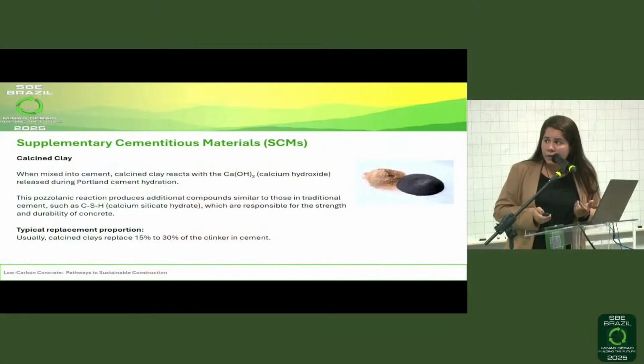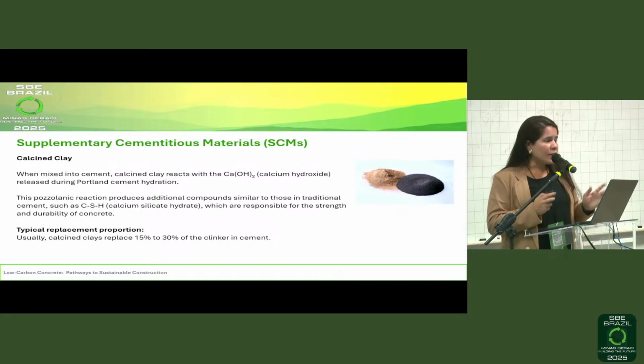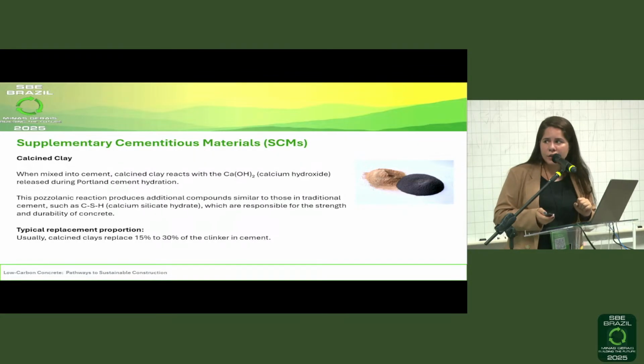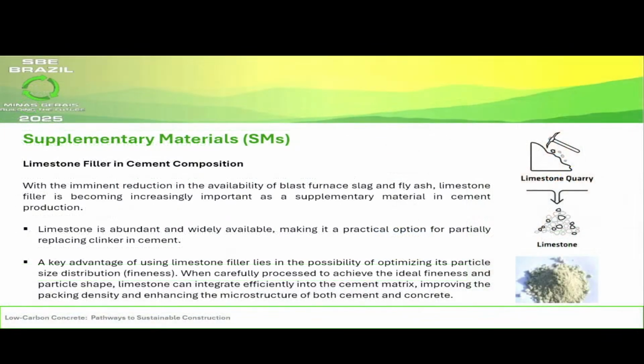Nowadays in Brazil, we don't work with this type of material, but there are other cement companies that work with this material, so that's an alternative. We usually work with substituting 15 to 30% of clinker using calcinated clay.